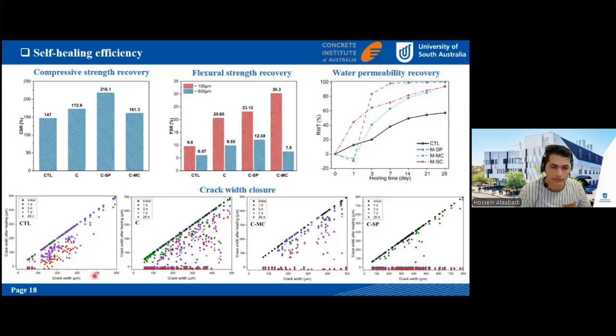Here, if you have a look at these bottom graphs, it's the crack widths at different points. We select different points in the cracks and measure the width of cracks after various times, like the initial cracks after 1, 3, 7, and 28 days of healing time. So you just see in the control sample, the maximum crack we could heal was around 150 micrometer, while the sample containing the very plain capsules, just sludge and calcium hydroxide, can heal cracks around 400 micron, even 450 in some specific areas. So the crack closure is around double that of the control samples.